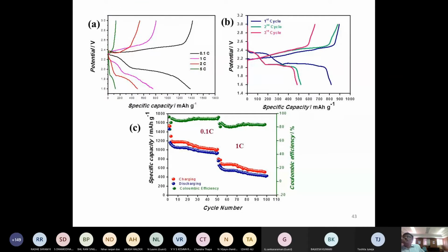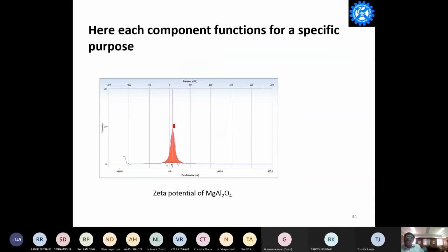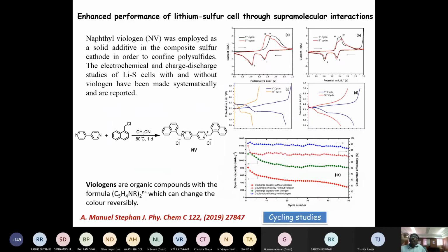And again, we subjected this cathode to charge discharge studies, and we could go beyond. When we used sisal carbon with sulfur, we were able to go only to 1050. But in this case, if you look at this figure A, we have gone up to 1400 milliampere hour per gram, and again we could go up to 100 cycles. We could not go beyond that, because the poor electronic conductivity of sulfur is not the only issue; it is one of them. In the same way, finally we measured the zeta potential. It shows the positive side, so because of the electrostatic attraction, it attracts the polysulfides. So it improves the cycling performance of the lithium sulfur batteries.